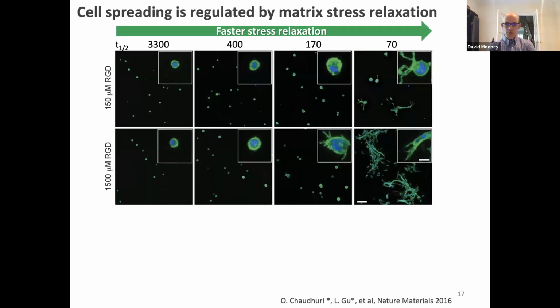So Luo and Ovi first took stem cells and put them inside these hydrogels. And they found something pretty interesting, which is that if the gels were identical in terms of the adhesivity to the cells and the stiffness, but the stress relaxation varied, the behavior of the cells was dramatically different. The cells in the more elastic gels stayed completely rounded up, stayed separate from each other, and really didn't do anything very interesting. But as the materials exhibited more and more rapid relaxation, the cells could spread within the materials, they could migrate within the materials, and they could proliferate.